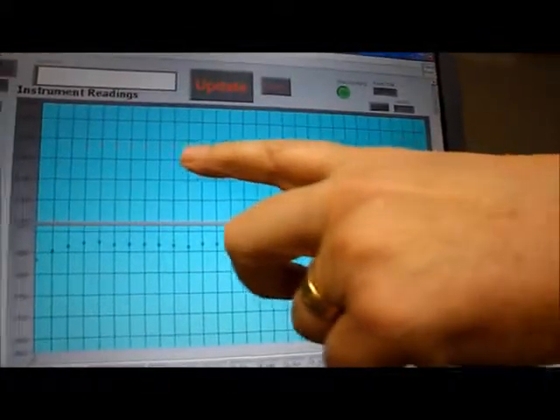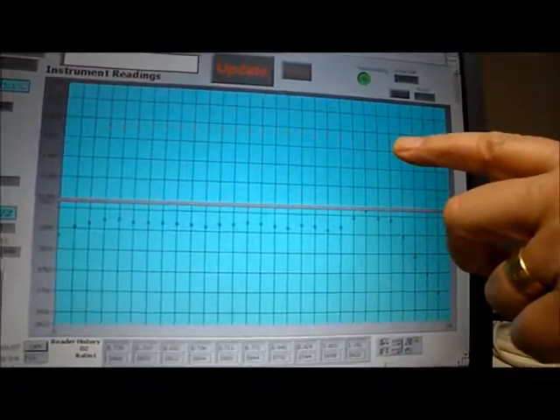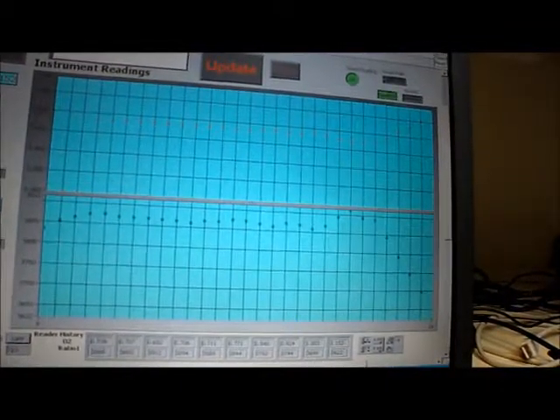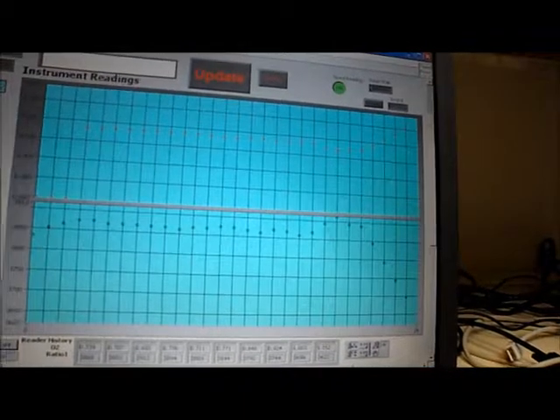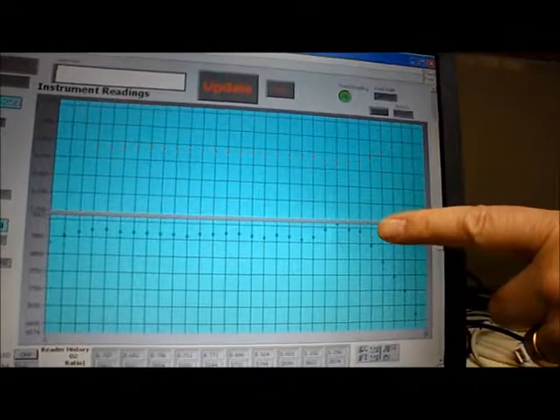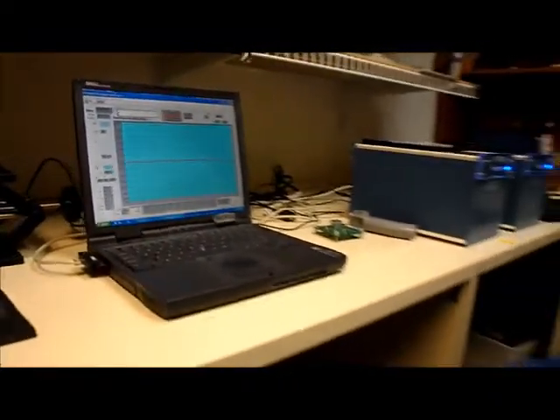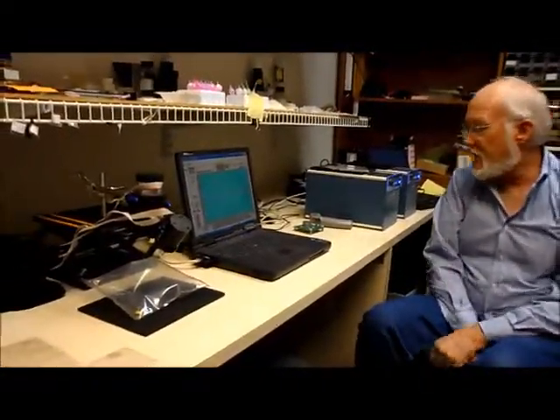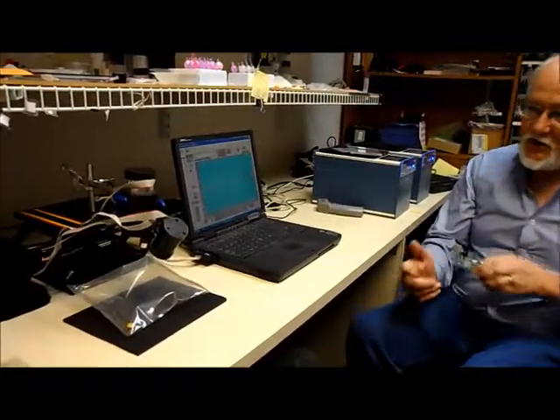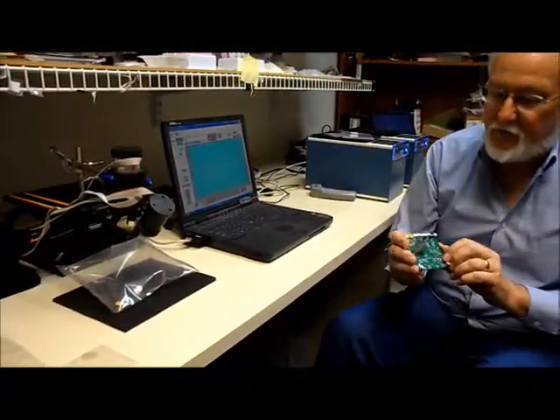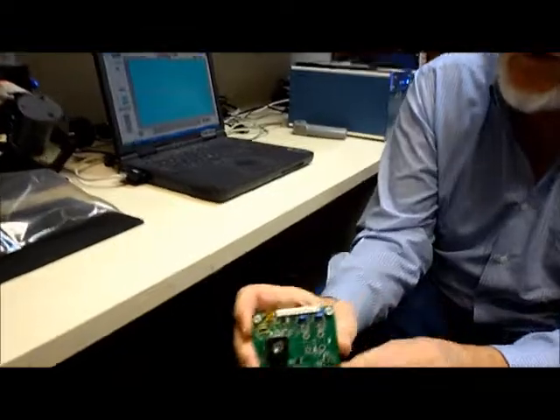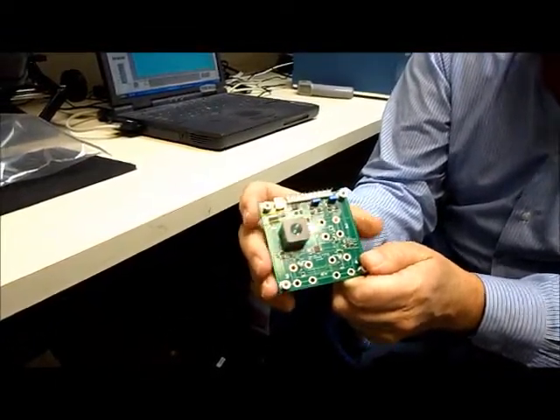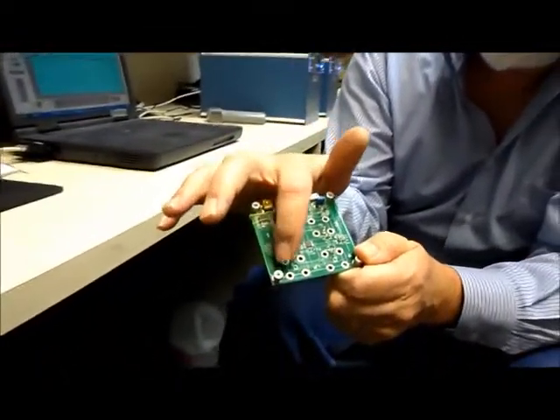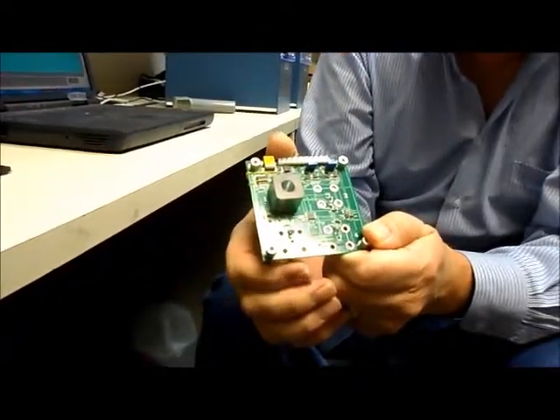This is where we had our measurements going on before I took the tape off the hole, and now this is the signal showing an increase in oxygen. Actually, what we're seeing, the instrument is detecting a decrease in the lifetime of the emitted signal from our oxygen sensing dye. This application of what you see was with earlier instrumentation, of which we have this now reduced to a small footprint here. On this board we actually have 4 independent oxygen readers present.